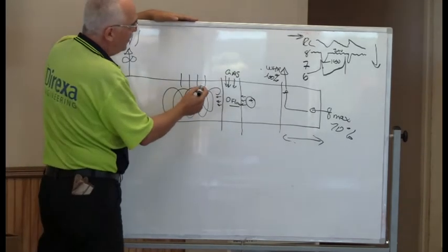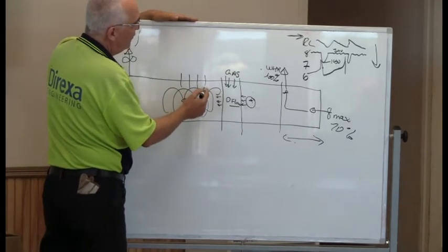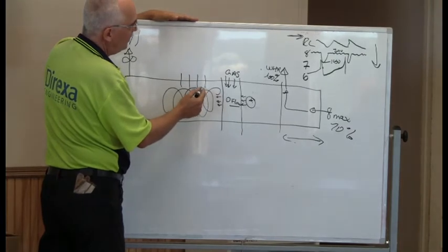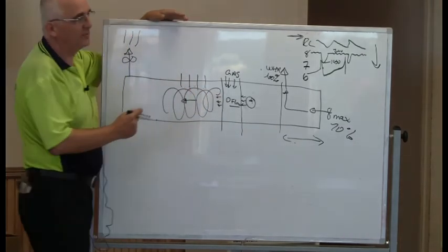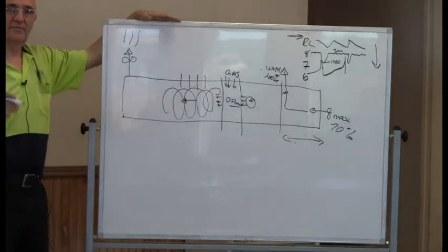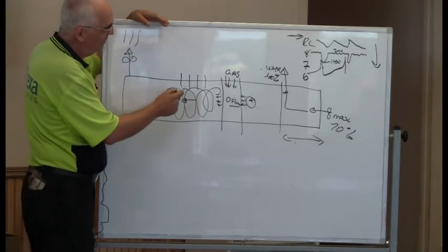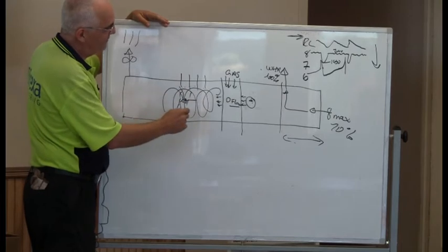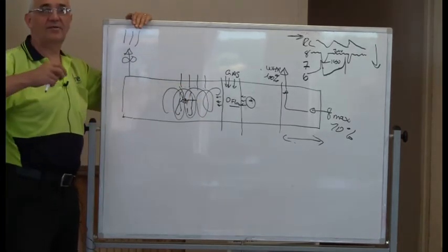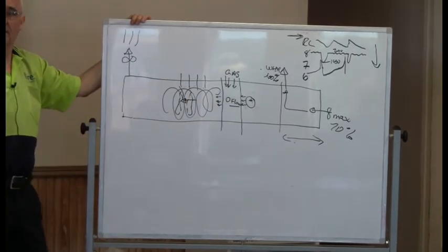But what you do is you force your stick burner without gas but with air, and basically you create a torch here where the air and the gas get into contact and combust.